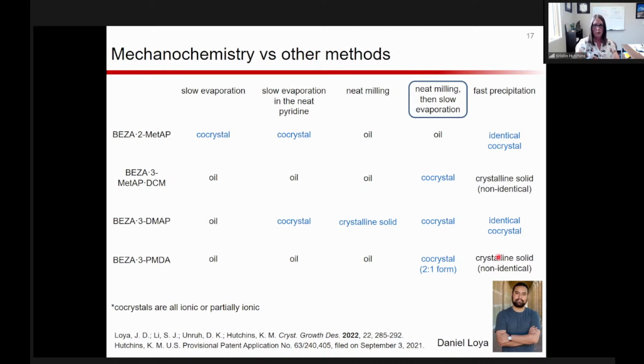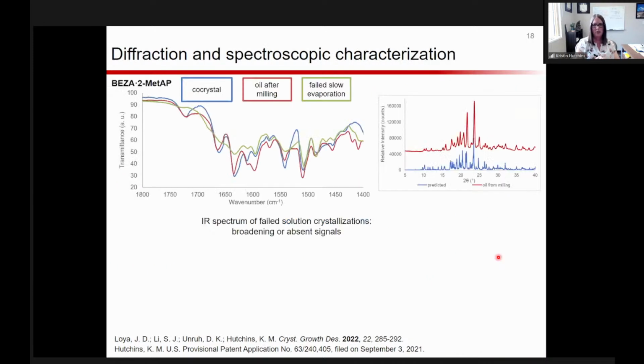So really at this point, we were curious, how is milling giving us these results? Because we're doing milling, then slow evaporation, we're putting it back in solution. How is that different than just doing slow evaporation directly? And so we decided to look at some IR spectroscopy. And what you're going to see is the co-crystal highlighted in blue, the product that we get from milling in red, and then in green, a failed solution crystallization.